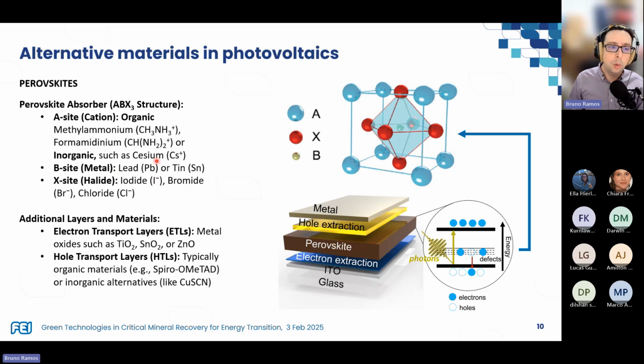So lead, we are starting to try and phase out lead use because of the waste pollution that you are probably aware of, and replace it with tin, but we still have issues with the robustness of the material, yes. So we still have a lot of research to do to improve the robustness and the reliability of tin perovskites. And as the X-site, we normally use halides, so iodide, bromide, or chloride, which are also gladly very widely available to us. But in addition to the absorber, which is the perovskite, we also have different layers.